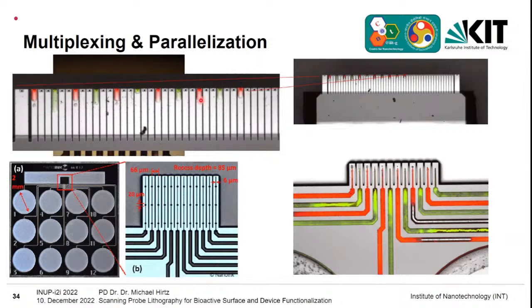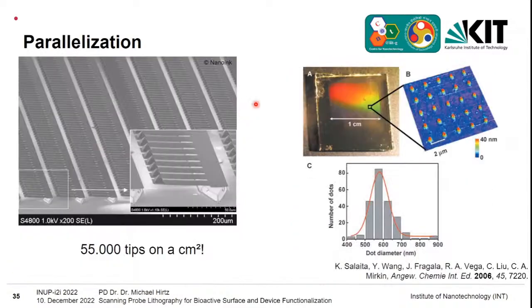You can also go from 1D to even 2D arrays. This is shown here. And then you can go really, with DPN, to fairly high surface areas. You can see here how it's structured, a 1 by 1 centimeter surface with this kind of dot array that is in the range where it can interfere with optical light. So it's like an optical diffraction mirror, let's say, or a grating. And you can see here nicely where the nano pattern spans over this very wide area.